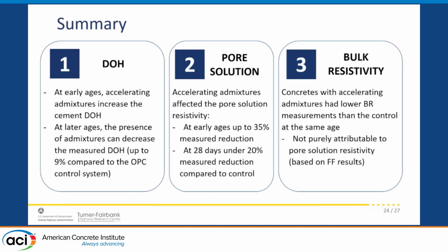So a little bit of a summary here. The degree of hydration - just because the accelerators increase the degree of hydration at early ages doesn't mean that they increase the degree of hydration at later ages. Some of them actually decrease it, and at 28 days, there was a drop up to 9% compared to the control without any admixtures.